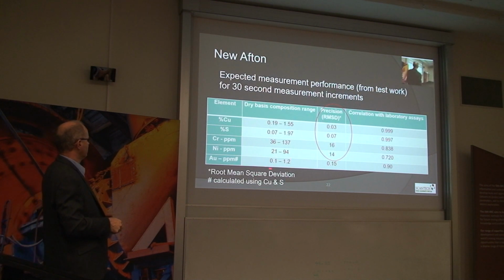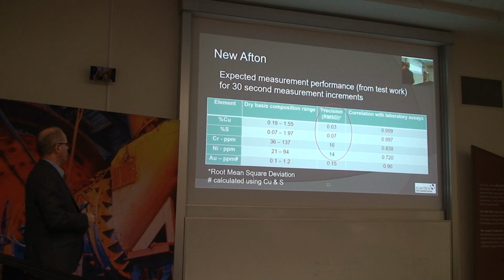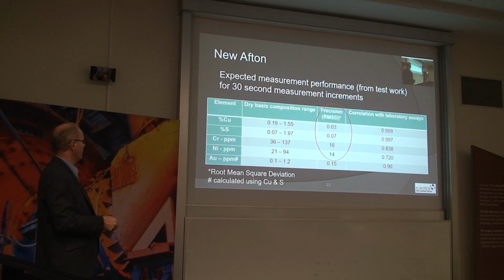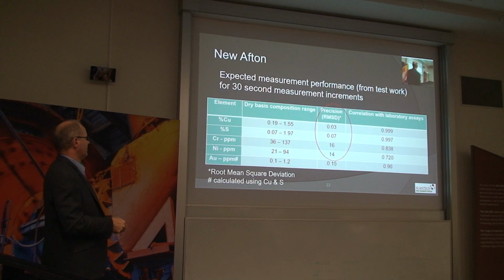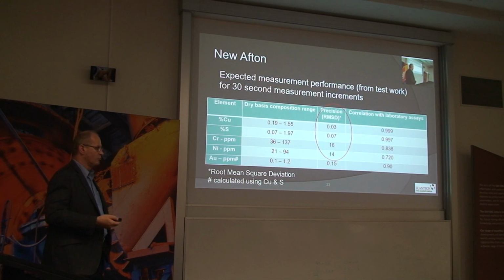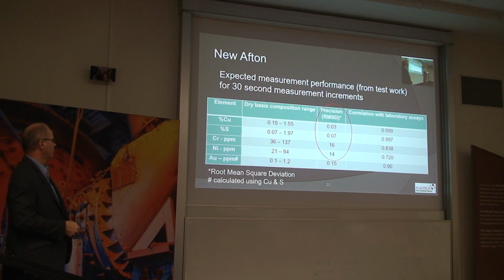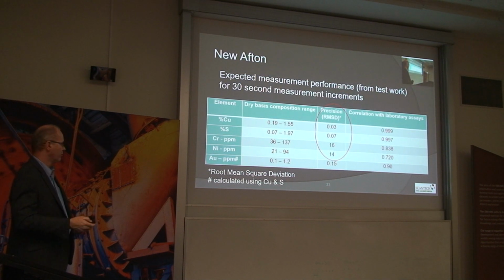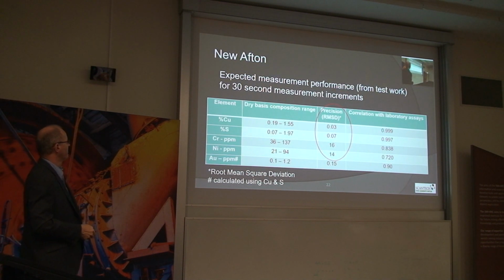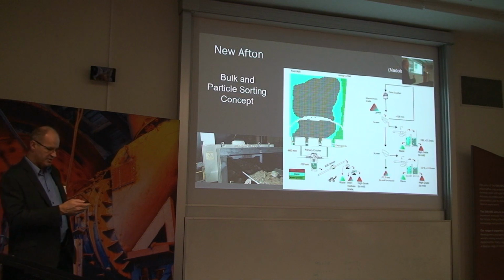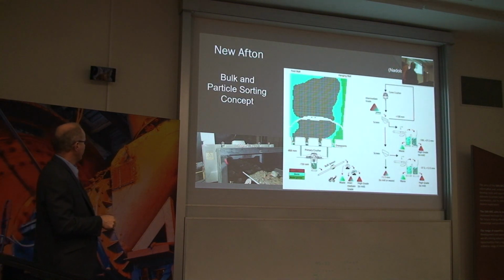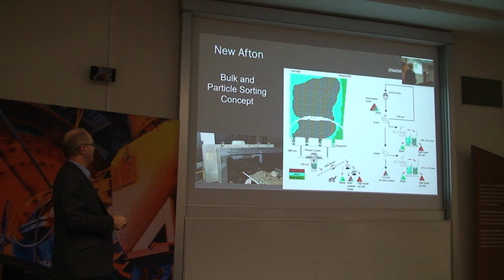And for gold, the range was between about 0.1 and 1.2 grams a tonne, and the calculated gold result was within 0.15 in terms of the root mean square deviation of those results. So they were happy to proceed. Picture of the installation of the analyzer underground, material coming out of the gyratory crusher. This is an image representation of their block cave.